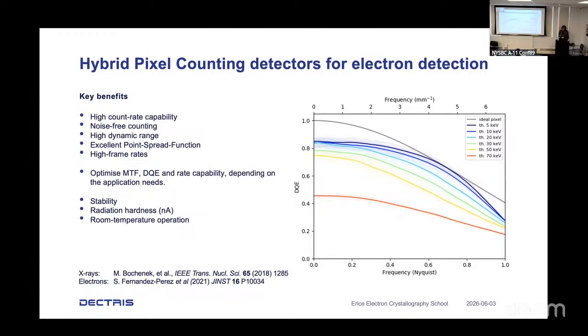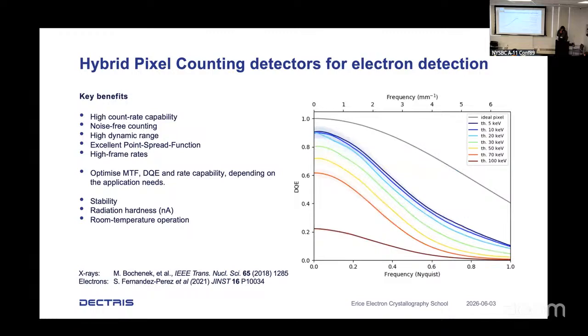Because we have direct detection, direct conversion, no scintillator involved, no fiber optic plate and so on, we have an excellent point spread function giving rise to good MTF and DQE. And because you can combine this digital readout with fast readout electronics, we can achieve higher frame rate. Here you see the DQE at 100 kilovolts in linear counting mode. As a function of the threshold, the higher the threshold, the faster the counting, but this reduces the DQE. So you can optimize if you want to work with high DQE or with high count rate. This is shown here for 200 kilovolt. And in addition to silicon sensors, we also offer high-Z sensors for work at 300 kilovolt.